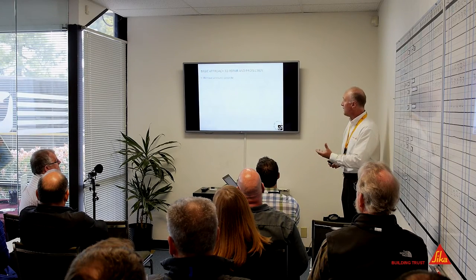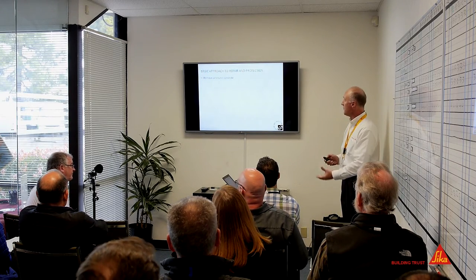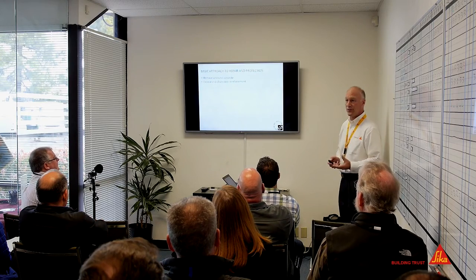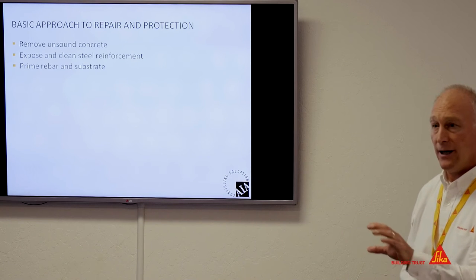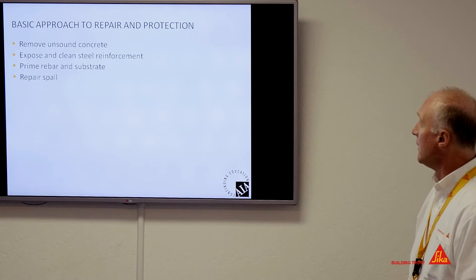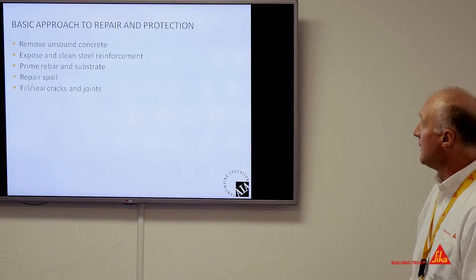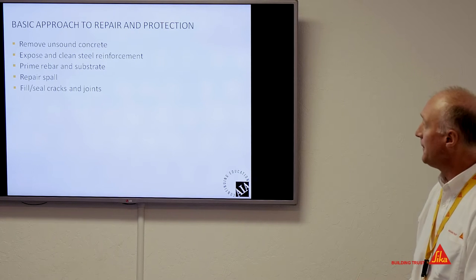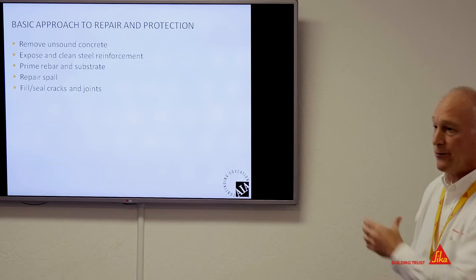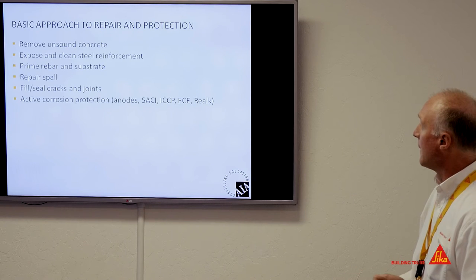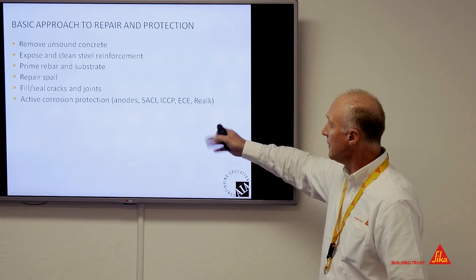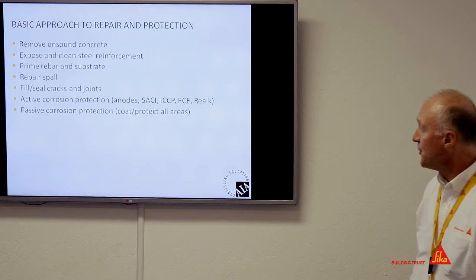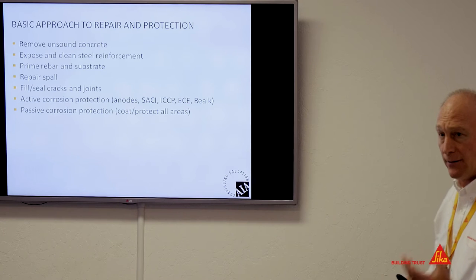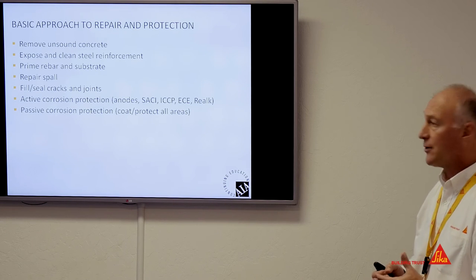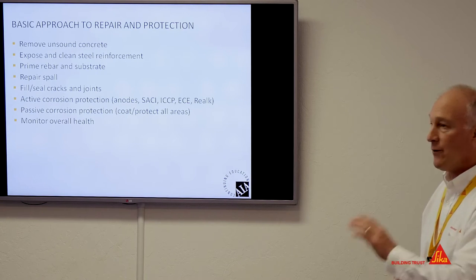So the basic approach that we take as an industry is we remove the unsound concrete, expose the reinforcing steel, we'll prime the rebar and the substrate. Then we'll do the spall repair, fill and seal all the cracks in the joints. Okay, so up until this point, this is all things I would call a repair. Then we do active corrosion protection. Then we do passive corrosion protection, which is coating and basically affecting the resistivity of the concrete. And then we monitor the overall health.